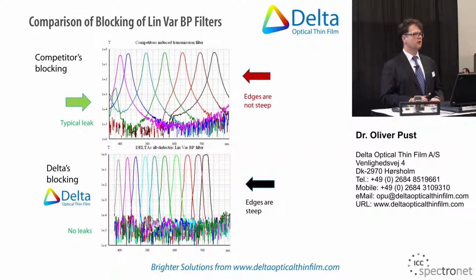Even more important, look at the blocking curve, the OD plot. Old technology, and you can see that the edges are far from steep, the blocking level is inconsistent, and you also have some leakage effects in the blue region. And for comparison, again, our filter with a nice deep blocking level of better than OD4, absolutely.